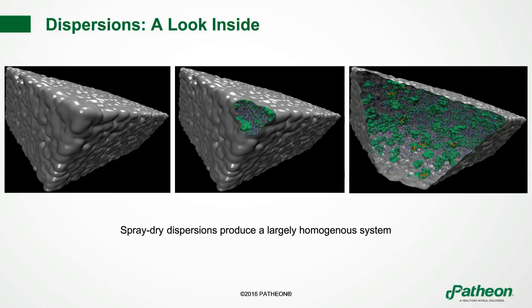The reason for that is because we're already taking the polymer and the drug prior to making the dispersion, and we're mixing it intimately in an organic solvent, like, say, acetone or tetrahydrofuran or ethanol. And so by nature, you've already created, quote, a dispersion with three components: the solvent, the polymer, and the drug. And then when you rapidly evaporate the solvent, you're maintaining that homogeneous structure in your dispersion. That might not always be the case with hot melt extrusion or other technologies that don't rely on the intimate mixing of a solvent. And so this might be one of the advantages that we see with spray-dry dispersions, is that we actually do produce this very homogeneous system.